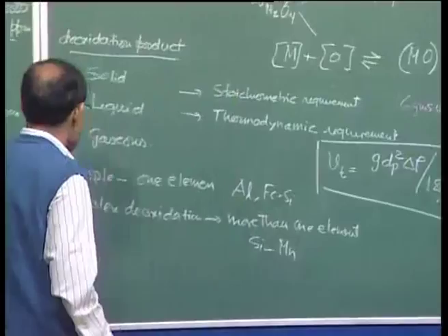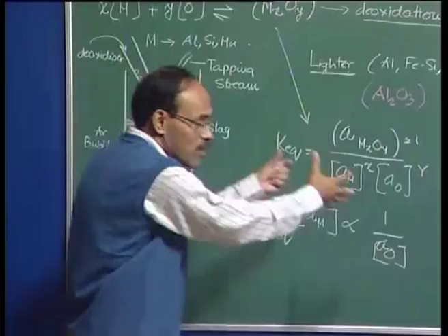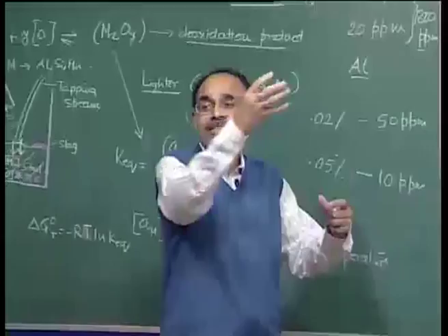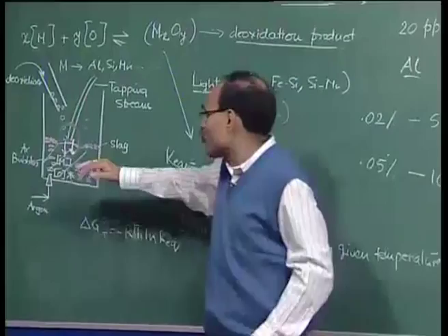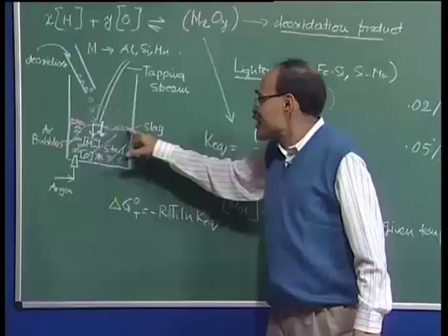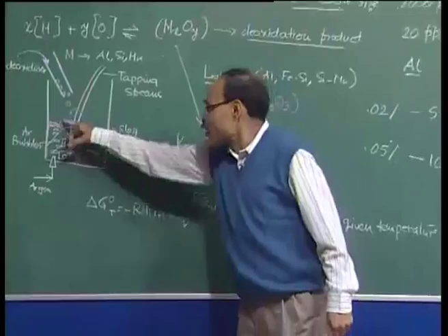So, once the ladle is filled up and you are taking it to subsequent stations, you get some time, and in that particular time, what happens? The deoxidation products which have formed deep inside the system have a chance to float up. So, you have to give sufficient time for these inclusions to float up to the free surface, where we have slags already forming, and these slags can capture the deoxidation products.